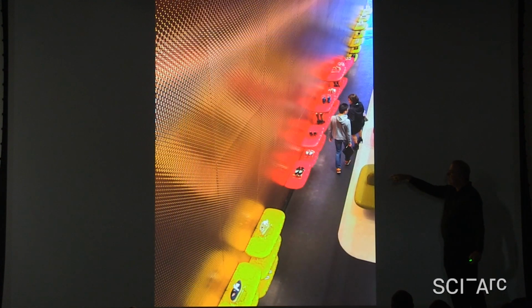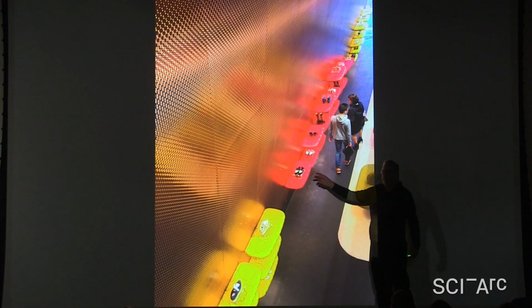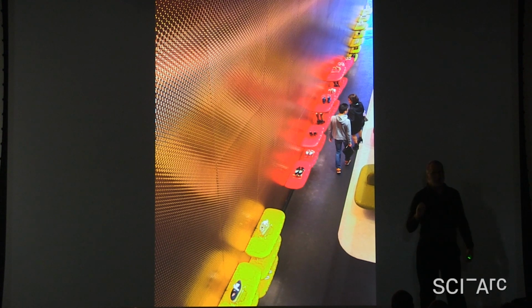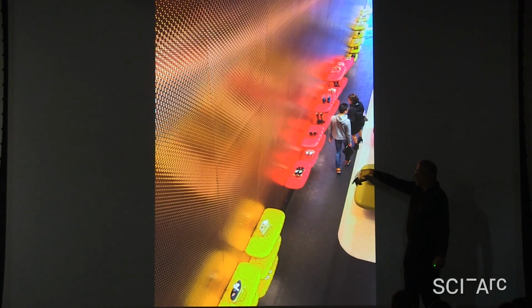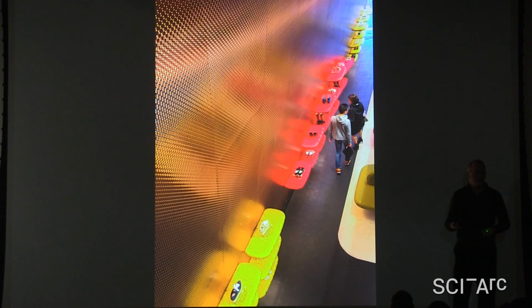But when you do the larger one, you'll see here, I've got some horizontal seams in the larger wall and vertical. What we found was as we were pressing the copper and putting these dimples in and out on the copper sheet, it stretched it slightly, just so slightly, so that if we start every sheet in the same direction, they're all going to stretch the same and it'll work. But if you start them and you have them intersect, you're breaking up a four-way joint, for instance, in this case, you have an intersection piece where one part has been elongated more than the other. So we have to get in and adjust things to predict how the metal is going to move. You can do it another way by changing the temper of the metal. But that's where, hopefully, our expertise fits in with the designer's interests, because they want this thing to be very monolithic in appearance.